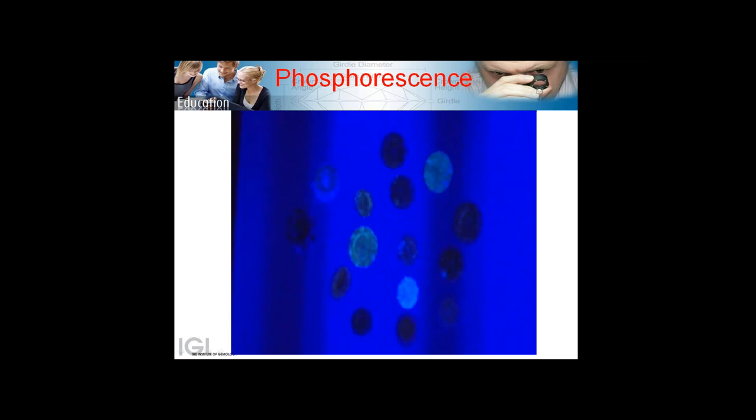So what happens is, we put it under the UV lamp. After a few seconds, we switch off the UV lamp. Now, if the diamonds still glow, you see here, two of these are still glowing. You clearly see them. So these are not natural diamonds. They are CVD.